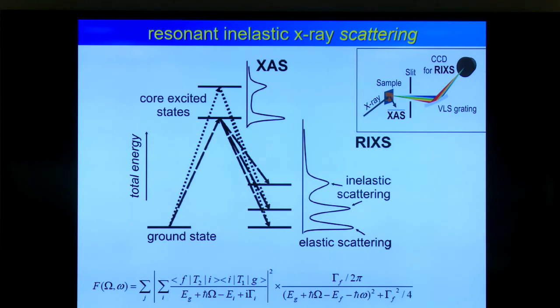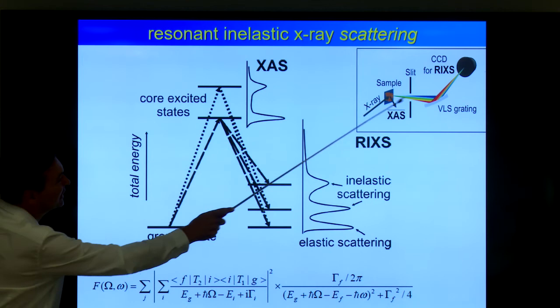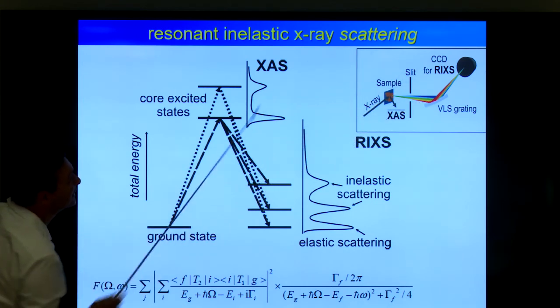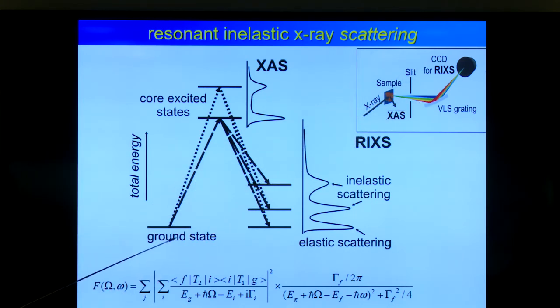So the experiment works like this. You do your normal X-ray absorption on the sample, and then you have your RIXS detector. You start from the ground state, you go to a core excited state, and go back to the elastic scattering or the inelastic losses. And you solve everything with the Kramers-Heisenberg equation. So you calculate the X-ray absorption from the ground state to the intermediate state, and then from the intermediate state to the final state, dipole or quadrupole, and then include interference effects and broadenings, and then you get your RIXS spectrum.